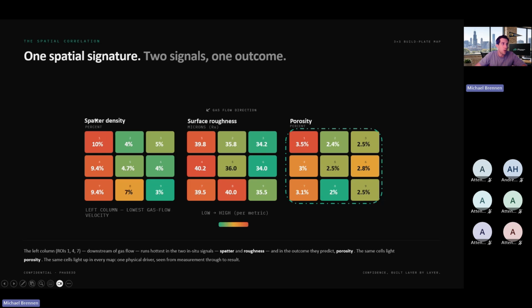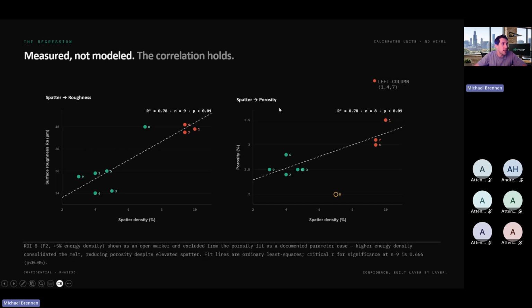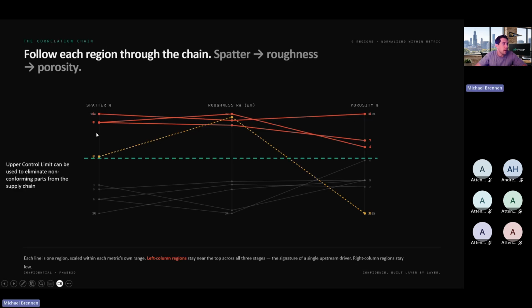So, our hypothesis coming into this would have been that increased spatter density will increase surface roughness, which will ultimately decrease density or increase porosity. And we see that when we plot this, we have a pretty strong R-squared value of roughly 0.8 with a good correlation between our spatter density and our surface roughness, and then our spatter density ultimately to porosity as well. When we plot these all the way across, we can again see the correlation between our in-situ metrics here on the left to the ultimate part performance here on the right.